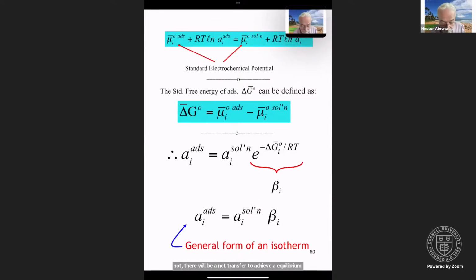And so if we look at how we get a little bit more quantitative, here we have the electrochemical potential for the adsorbed species, the electrochemical potential of the solution species, RT ln of the activity, RT ln of the activity. These, as we mentioned, are the standard electrochemical potentials. And when we equate those, we can then look at what the free energy of adsorption is by comparing the differences in the electrochemical potentials. So we can define the free energy of adsorption in terms of the two components, for the adsorbed species and the species in solution.